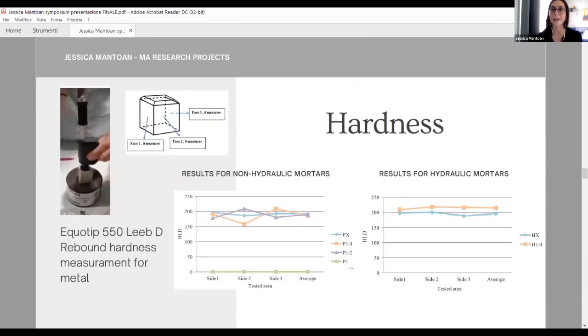After that, I decided to carry out a hardness test. As probably someone noticed from the picture of the preparation of the mortar, my samples were of quite small dimension in order to speed up the carbonation process. But unfortunately, this decision created a lot of problems regarding the choice of a method to measure the hardness of the samples. That's because typical instruments that are used to measure hardness for concrete and stone, for example, Schmidt hammer or durometer, were not designed to be used on such a small material.